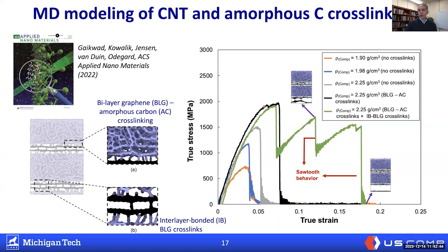We see that we can increase the strength, so that is the black versus the gray line here. We can increase the strength quite a bit. A little bit more dramatically, we can increase the toughness. So the total area under this curve grows quite a bit. Now, what we did see, though, is that even if we put that crosslink in there, there's still no load transferring from one side of the nanotubes to the other. So then we put little crosslinks in between the carbon nanotubes, and we get this green line, which now tells us that we can dramatically increase the toughness of these materials if we can control where these crosslinks go.